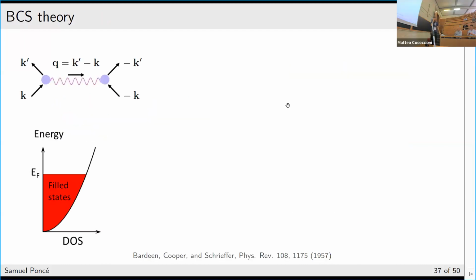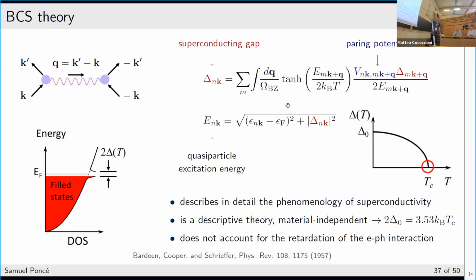So the superconductivity. This is the phenomenological original BCS theory, in which you are forming Cooper pairs. You have two electrons that are interacting via a phonon, basically creating this sort of quasi-particle picture, and below the critical temperature they can travel with almost zero resistance. What is happening also is that here you have the density of states, you are in a metal, so you have the Fermi level, and once you go below the critical temperature, you are actually opening what is called the superconducting band gap.